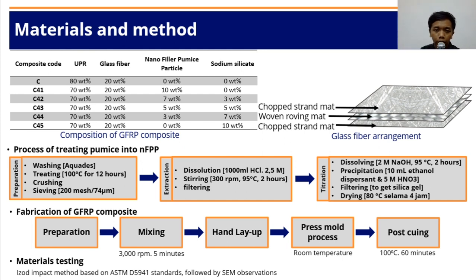The fabrication process was executed by a hand layup method followed by a press mold process, which was performed at room temperature. After the process is complete, post curing is executed at 100 degrees Celsius for 60 minutes. After the completion of the fabrication process, GFRP composites were prepared with length, width, and thickness of 64, 13, and 3 mm respectively, 7 pieces per variant for impact testing, which would be carried out using the Izod impact method.